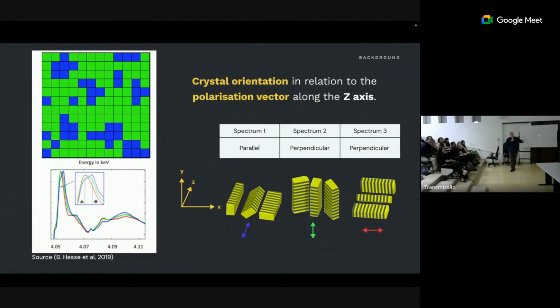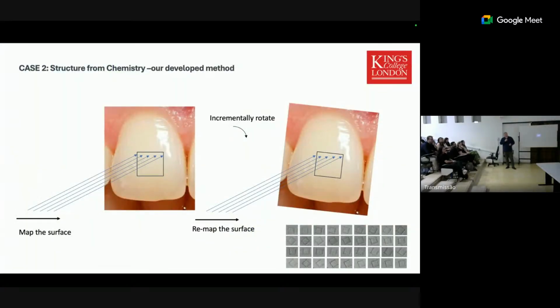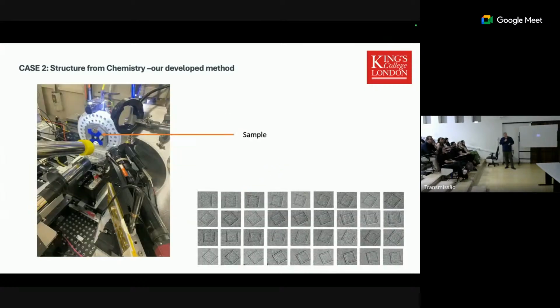Because if you look carefully at the graph at the bottom, there's only 2 options. And we want to have a third option. So to get around that third option, we rotate the sample, and then we can identify the third piece of orientation. So the work that we've done here for the first time is to map the surfaces at 2 energies associated with the calcium absorption edge, and then by rotating the surface, we can start to develop an understanding of crystal structure.